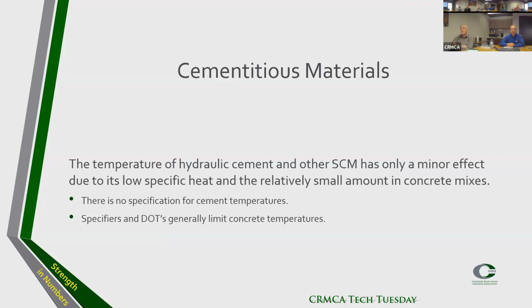The temperature of the cement or the SCMs generally has a minor effect because of its low specific heat and small amount in concrete mixtures. There's no specification for cement temperatures. Generally, specifiers and the DOTs, they limit the concrete temperatures and not the cement, aggregate, or water temperature. They only look at the concrete. And it is difficult. Once you have the cement on site, it is difficult to cool it down further.